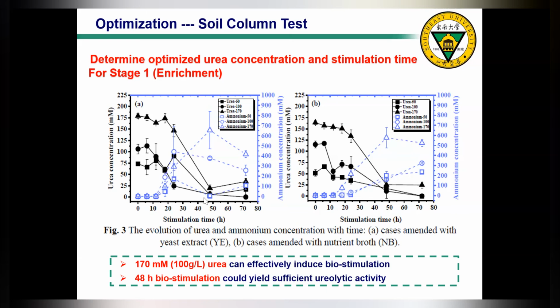Then we also find that after 48 hours, regardless of the medium, whether it is YE or NB, all given urea has been consumed. It means that after 48 hours, it's already done. We already have a sufficient amount of ureolytic activity from the stimulated bacteria. So that's why we choose 170 mM urea and 48 hours for our following tests.